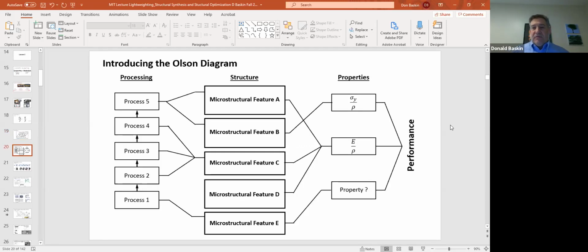One framework for designing materials is called the Olson Diagram, shown here. This is a framework for understanding that when you make a material, you have to do different processing steps. You might have to cast it. You might go from a liquid to a solid in a casting mold. You may have to solution treat it, heat it up, let it homogenize, and then you might have to quench it, and then you might have to do some hardening or some aging to the material. These different processing steps lead to different microstructures and different microstructural features. So there are really, in a lot of materials, what's called a hierarchy of different features in the microstructure.